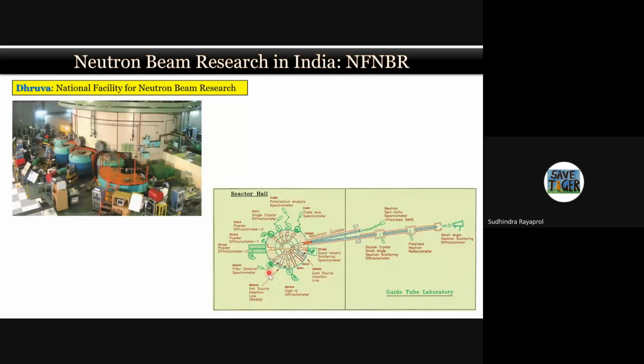There is a new beamline for imaging which has already come up, which is not present in this image. Then you have a high Q diffractometer where you can measure diffraction patterns up to very high angles. Similarly, you can do small Q experiments, called small angle neutron scattering experiments, on two instruments. You have a polarized neutron reflectometer where you can study thin films, and like that there are other instruments present in the Dhruva reactor hall.